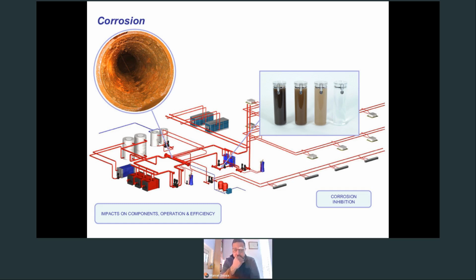The direct impact of corrosion is the loss of metals and leaks, structural integrity, the seizing of components such as valves, pumps and seals, and also leads to a reduction in heat transfer efficiency. Research suggests that just a 2 millimeter layer of corrosion actually reduces the heat transfer efficiency by as much as 5%. And the indirect impact of corrosion is particle generation, and these particles begin to clog up heat transfer surfaces and components.